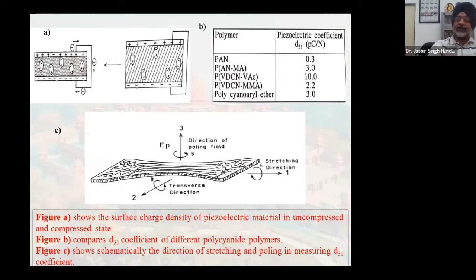Now, this is the piezoelectric coefficient which we get for cyanopolymers. For example, for PAN, it is 0.3. The reason I have already explained: the structure is a helical one and the CN dipole isn't able to move. PVDCN, polyvinylidene cyanide vinyl acetate, is a copolymer. It has the best piezoelectric coefficient, around 10 picocoulomb per newton.